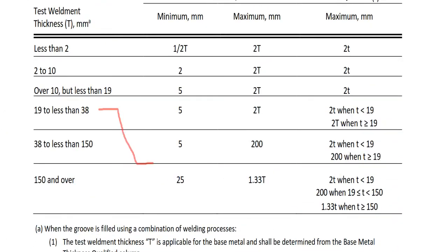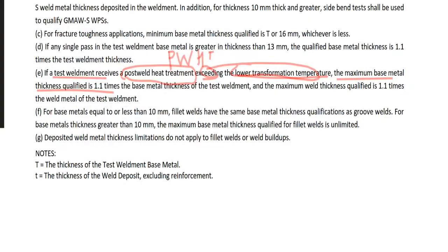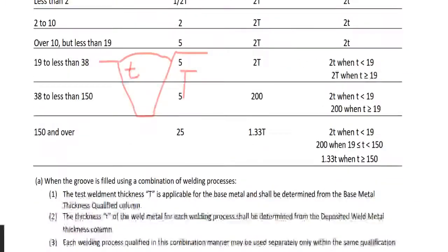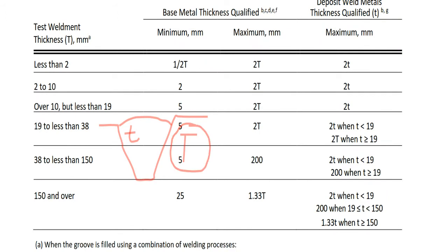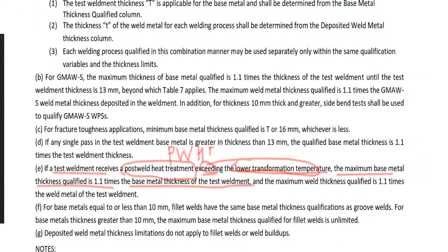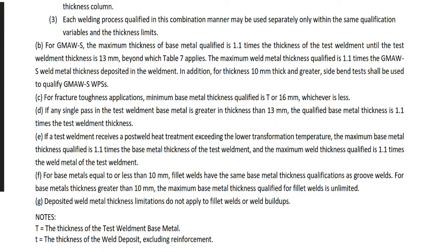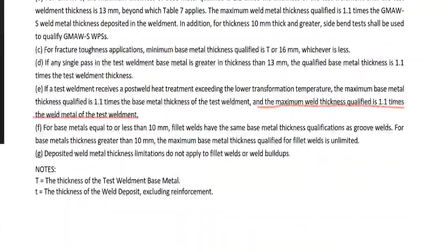So say we have a groove weld, and this is T, and this is small t, and in here the maximum base metal thickness qualified is 1.1 times the base metal thickness of the test weldment. So this T, the capital T, let's say this is 10 millimeter, then this second line is applied, so 2 millimeter to 10 millimeter. But the maximum qualified is 10 times 1.1, it's 11 millimeter. So the maximum qualified of the base metal is 11 millimeter. This was E. And the maximum weld thickness qualified is 1.1 times the weld metal of the test weldment. The same thing applies: the small t times 1.1.